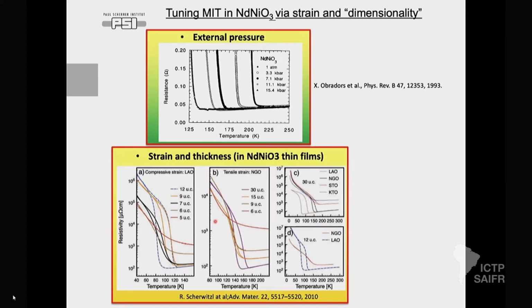What I said before, right? The main parameter which we are now going to explore is the metal insulator transition. You could see how this was going up and down, depending on the rare earth you use to stabilize the crystal structure. However, if we now focus on neodymium nickel oxide, NdNiO3, as I said before, we already have the nickel-oxygen bond under tensile strain or internal pressure. So now if you use external pressure, you could see that you can further tune the metal insulator transition pretty efficiently. So for the system which is at ambient oxygen pressure, you have the metal insulator transition around 220 or a bit lower.